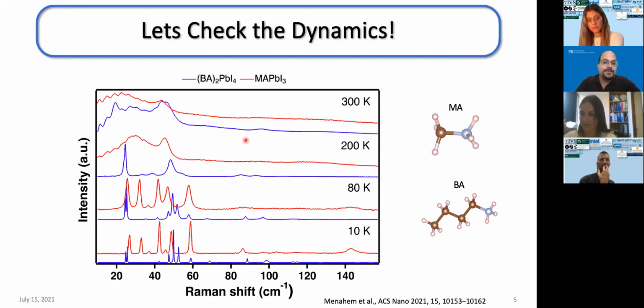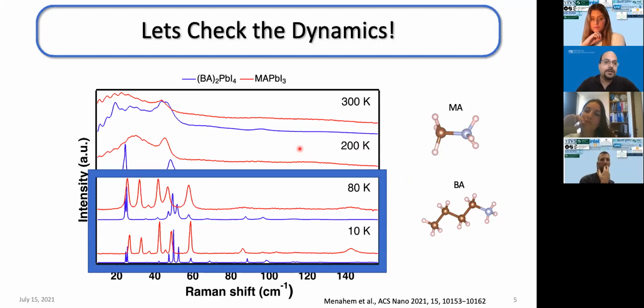Let's start the comparison of the structural dynamics. As I said, I started by comparing the temperature-dependent Raman scattering of the 2D perovskite butylammonium lead iodide and its 3-dimensional counterpart methylammonium lead iodide. On the right, you can see the corresponding A cations. The 2D perovskite is the blue curves and the 3D perovskite is the red curves. Now, if we focus specifically on the low temperature range, we see that their structural dynamics are very similar. We see the same number of peaks in relatively the same positions with comparable widths.